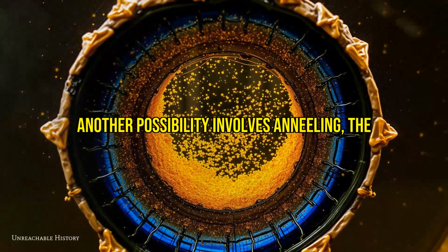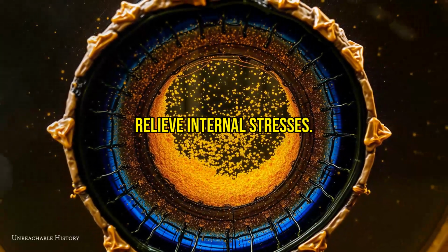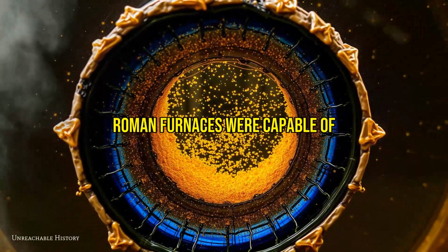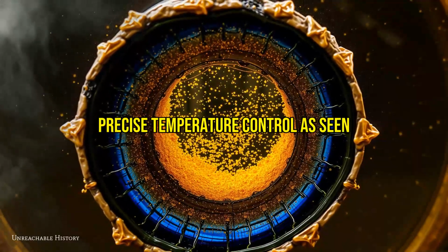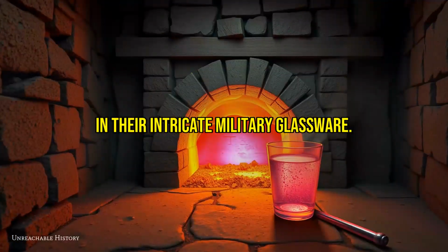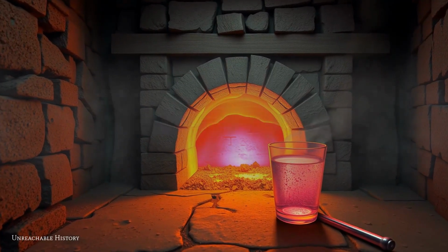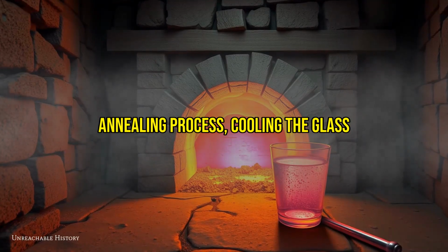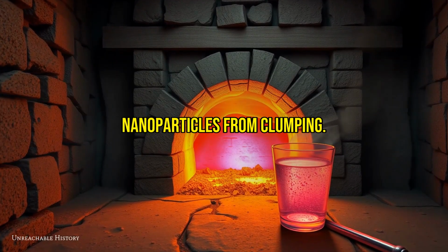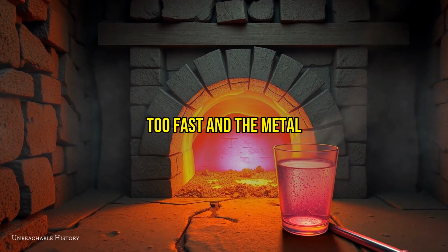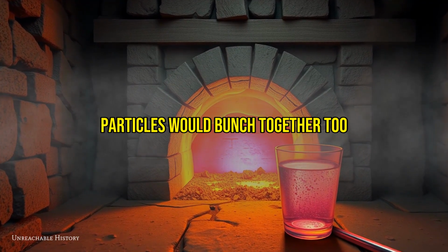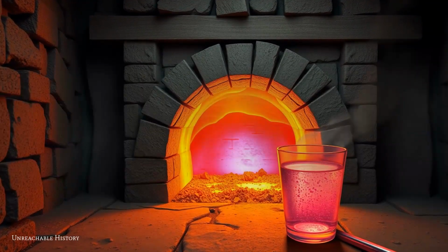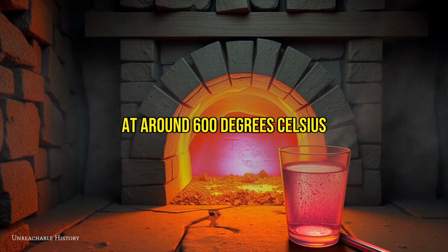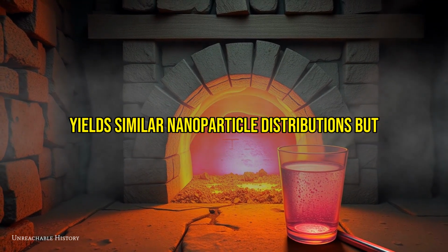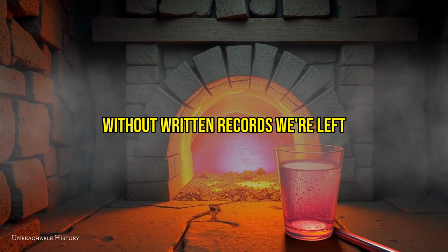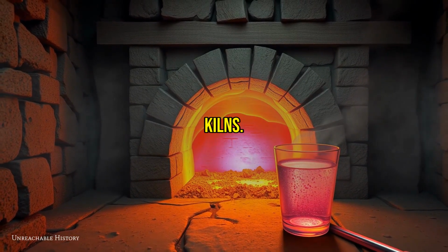Another possibility involves annealing, the slow cooling of glass to relieve internal stresses. Roman furnaces were capable of precise temperature control, as seen in their intricate millefiori glassware. For the Lycurgus Cup, artisans might have used a multi-stage annealing process, cooling the glass at specific rates to prevent nanoparticles from clumping. Too fast and the metal particles would bunch together; too slow and they might grow too large. Modern experiments show that annealing at around 600 degrees Celsius yields similar nanoparticle distributions, but without written records, we're left guessing how Romans calibrated their kilns.